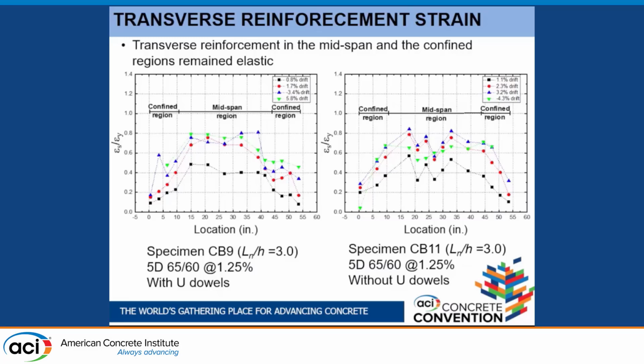In all cases, that ratio was less than 1, meaning all the transverse steel remained elastic, even in the plastic hinge regions. I should mention that for the middle portion, we were able to count on 4 square root of F prime C in PSI of contribution from the fiber reinforced concrete.